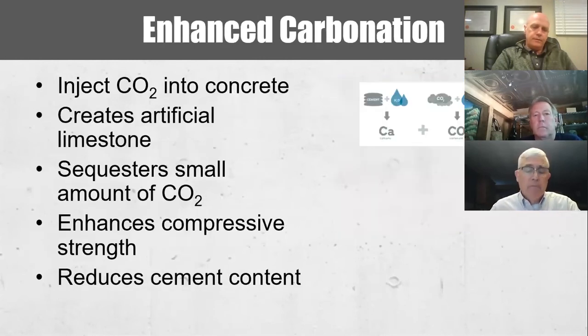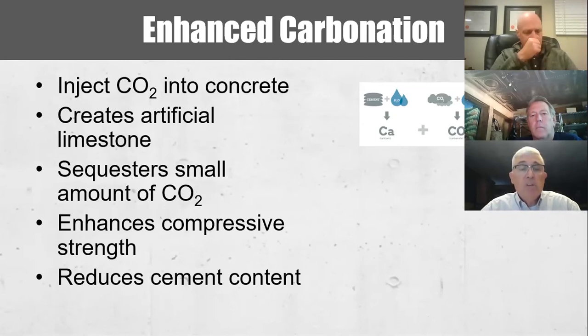So there are a number of entrepreneurs that have looked at this natural carbonation process and have been successful in developing ways of enhancing the production of concrete products by taking advantage of this ability of concrete to absorb CO2. One such process developed by a Canadian firm takes purified and liquefied waste carbon dioxide captured from various industrial processes, and it injects this CO2 into the concrete during the mixing operation. And in that process, there's a creation of artificial limestone, or mineralization, within that ready mix. The developers of this process indicate there's a small amount of CO2 that's sequestered in this process, but probably more importantly, the compressive strength of the ready mix produced with this process is improved, which allows you then to reduce the overall cement content in the mix.